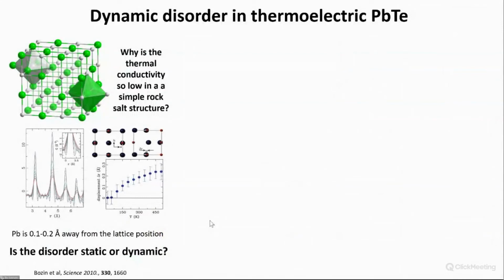I'll instead just point out another system that has been studied tremendously in thermoelectrics, the most famous thermoelectric, lead telluride, because lead also has these stereoactive lone pair 6s electrons, and this is what's behind this very strange behavior. This is Simon's famous Science paper from 2010, with Emil Bozin, right? That basically said, from the analysis of the 1D PDF here, you could see that lead seems to be, or is, off-centered from the sodium chloride lattice position, and it has a temperature dependence. And this, of course, intrigued me also, because this is a heavy lead atom that's off-center in a very simple structure, and this can explain why the thermal conductivity is so low.